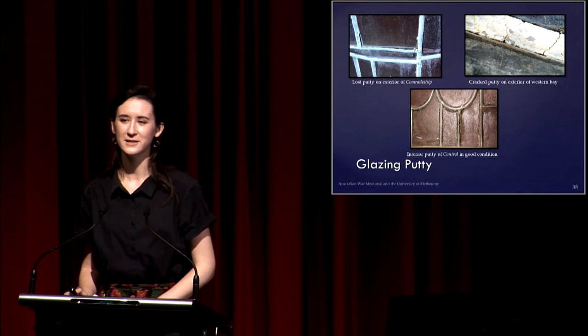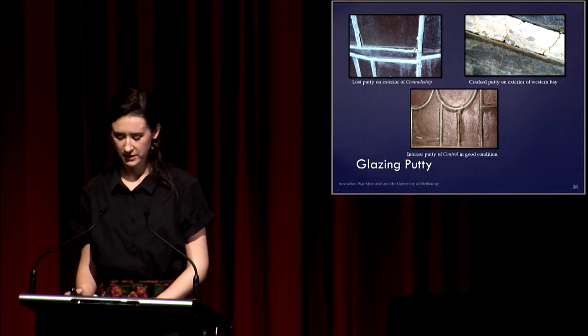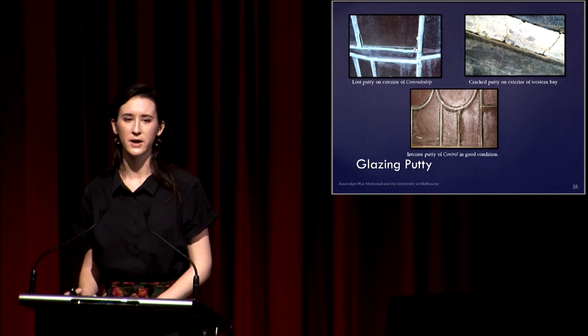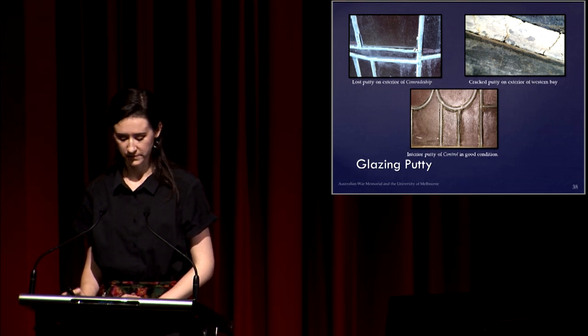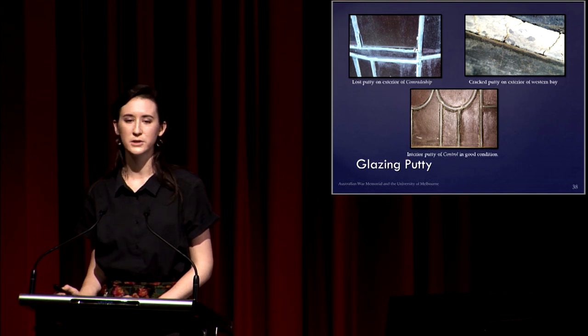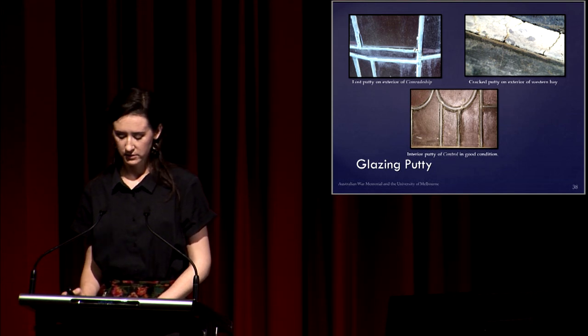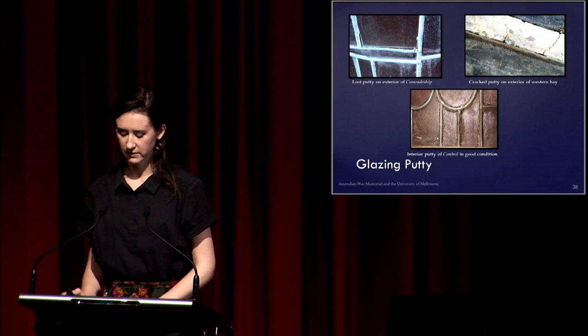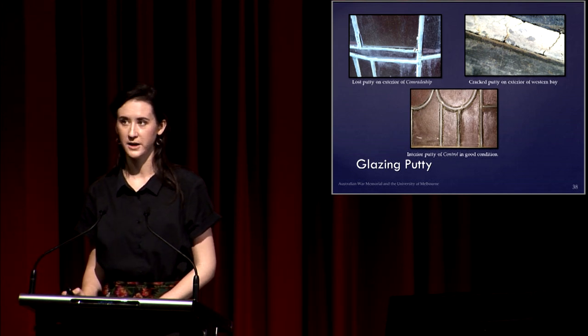The exterior putty is normally seen as a sacrificial element that needs to be replaced before it begins to fail, and this could be anywhere between 5 to 15 years, depending on the environment. Interior putty is generally protected from these conditions and doesn't usually need replacing for a much longer timescale.